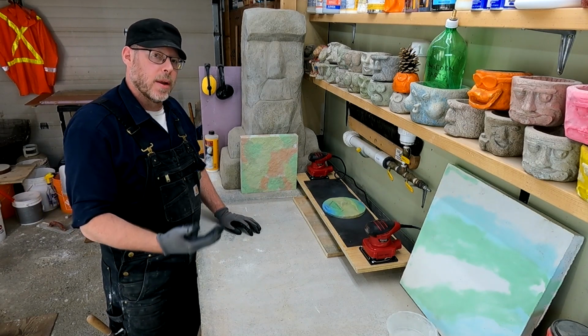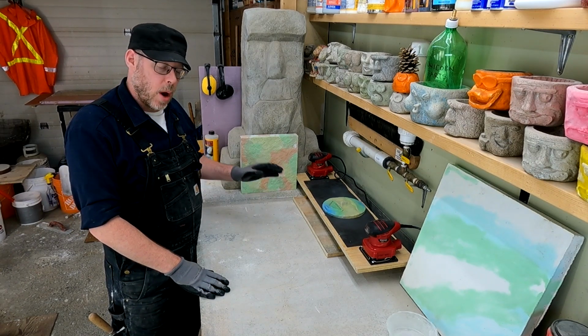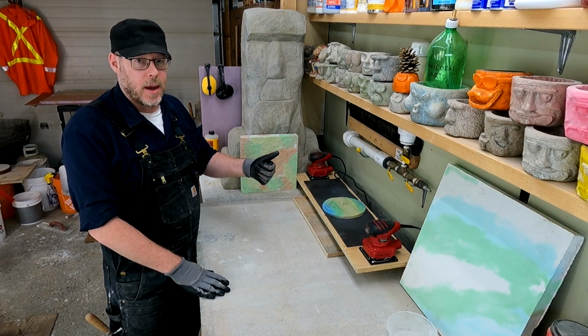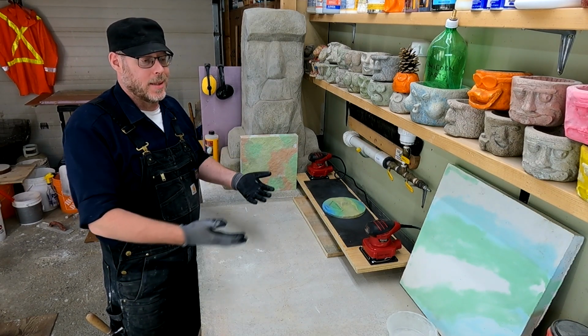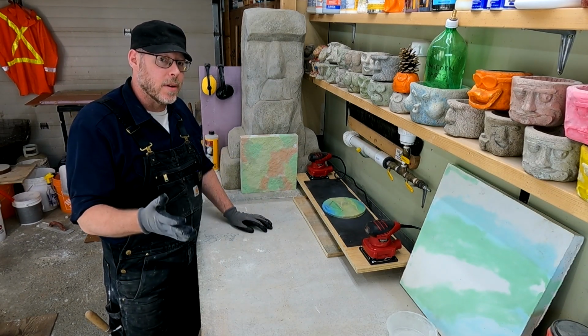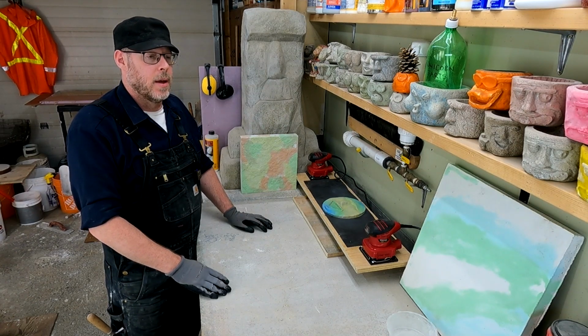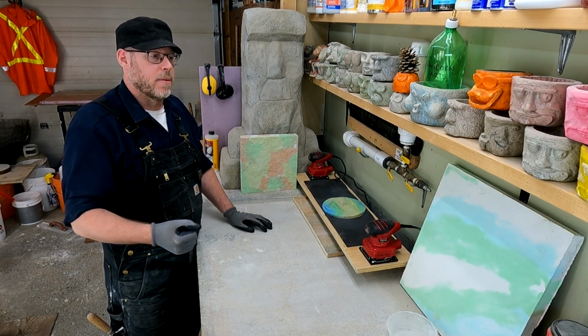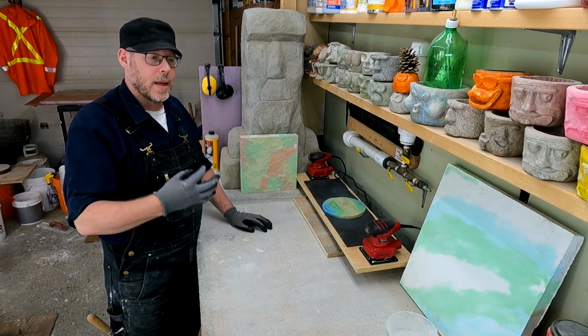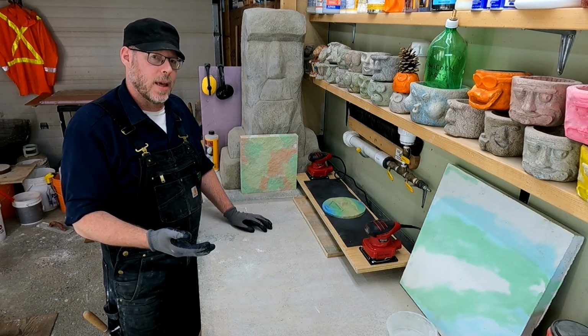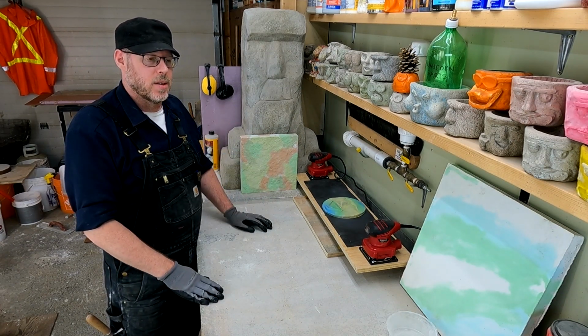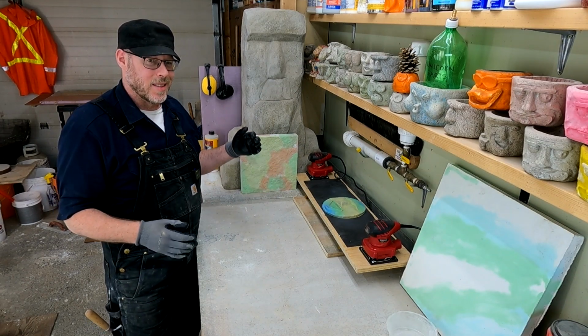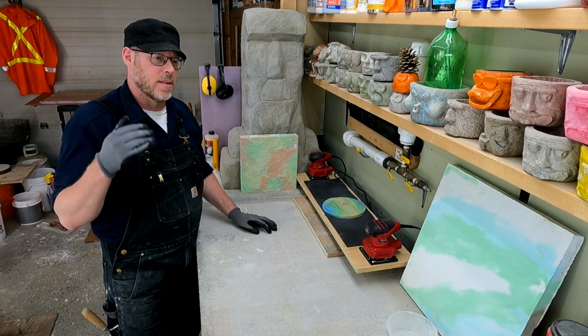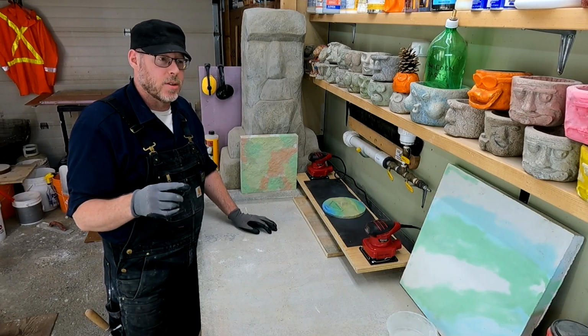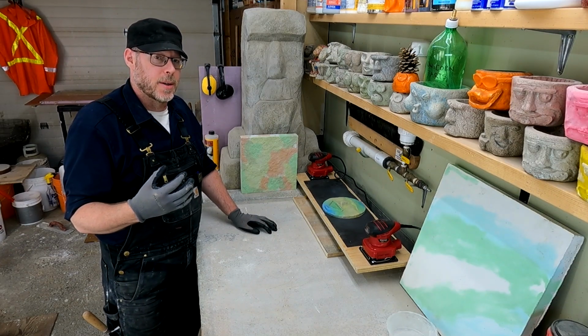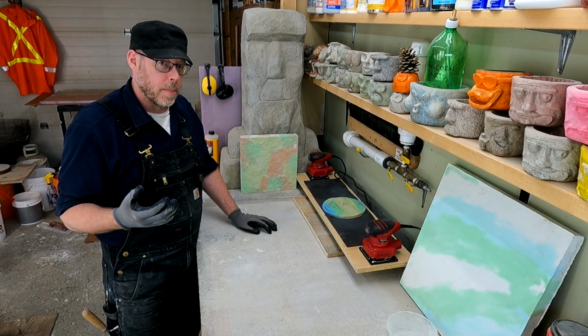And that's probably one of the reasons you're looking towards dry pouring this concrete. I mean, it's easier because you're not having to mix it, but it's also easier because it's essentially flat already. So you're not really even doing any finishing of the surface. Even if you do some finishing of the surface, again, with all this honeycombing and air pockets, you're not going to be able to get a true smooth finish to it. So now we've got concrete that's not as strong, it's not encapsulating the steel. The surface looks bad visually, but it's also porous and pockmarked, which allows a greater water permeability.